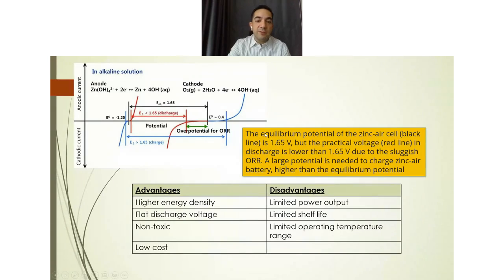To conclude the advantages and disadvantages of the zinc battery, we can mention the higher energy density, flat discharge voltage, they're not toxic, at least based on the metal element, and they are very inexpensive. But for disadvantages, we should highlight the limited power output with regard to HER that I explained earlier, and the limited shelf life that can be due to many aspects of cathodic and anodic, and I will explain this further on. Also the operating temperature range is limited because this is an aqueous battery, and if the temperature is very high, then we may lose the water content from the system.